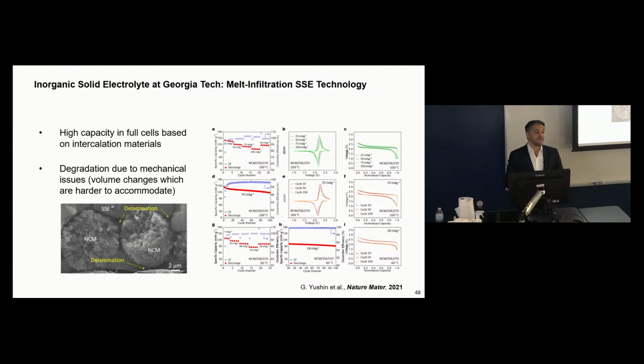Liquid electrolytes are very good in accommodating these volume changes. But if you have solid ceramic electrolyte, the accommodation is much, much harder. And so to overcome it, you have to figure out either how to design cathode particles that would have, again, even smaller volume changes, preferably below 1% volume changes at the particle level, or figure out how to deal with the interfaces, making sure it can accommodate some of the swelling at the interface between active material and electrolyte.